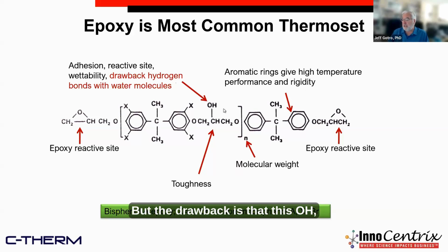But the drawback is that this OH hydrogen bonds to water molecules. So if water absorption is really important, epoxy might not be the best choice. There are other materials now that have much lower moisture absorption. And we'll talk a little bit about those very briefly coming up.